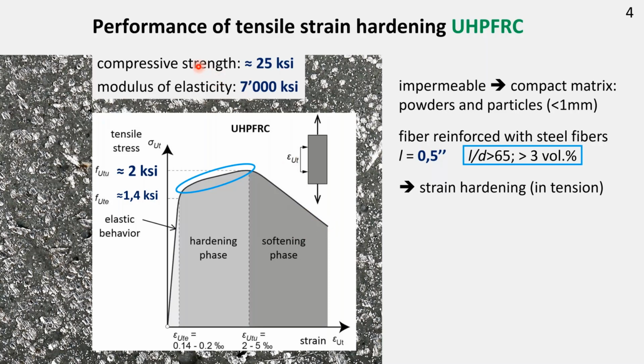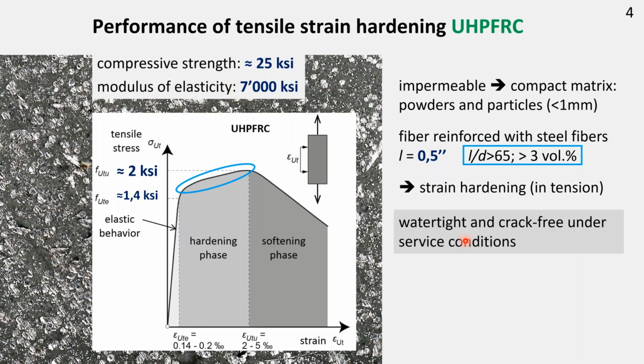The compressive strength is at around 25 KSI. So the tensile strength is 2 KSI. So we still have a ratio of about 1 to 10 or 12 between tensile and compressive strength. Modulus of elasticity at 7,000 KSI. The material is watertight and crack-free under service conditions. I will explain that in a minute.